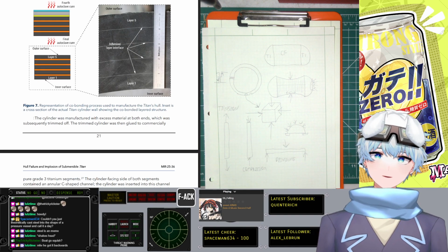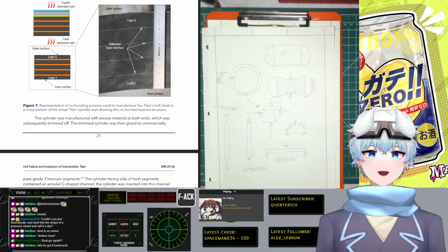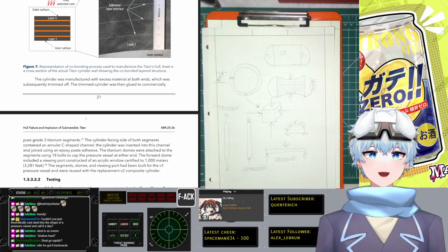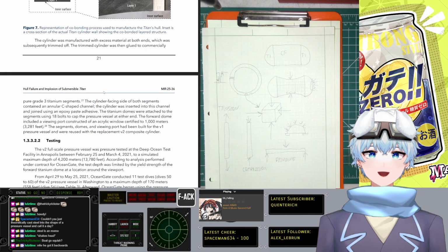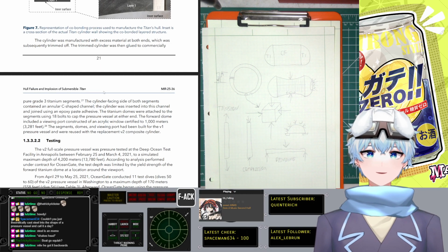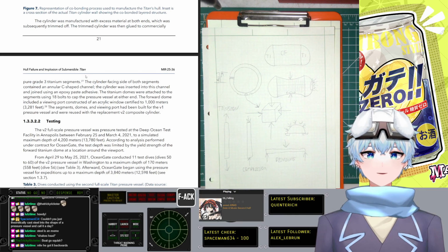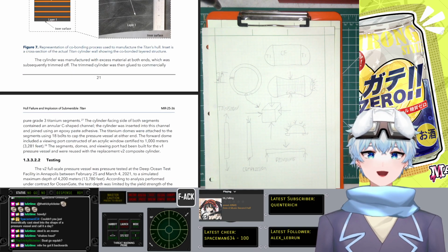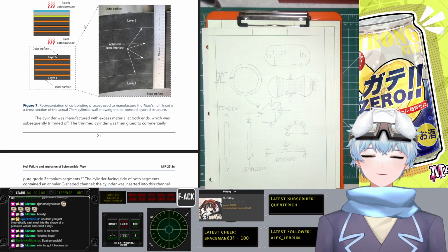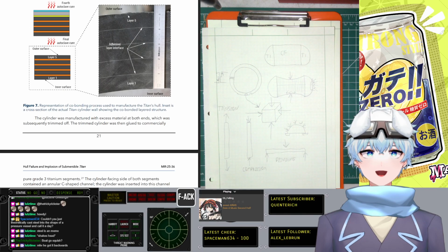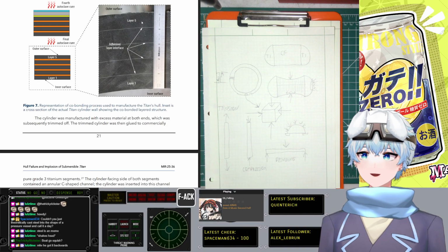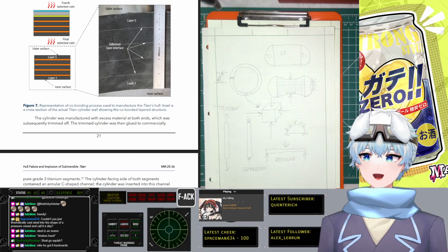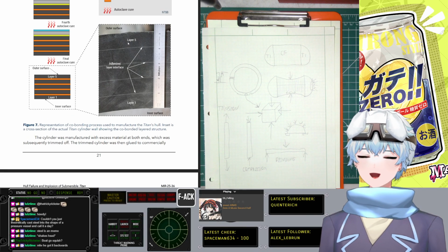So they say here, its cylinder was manufactured with excess material at both ends, which is subsequently trimmed off. It is then glued to commercially pure grade 3 titanium segments. There was a C channel to hold it in, and what ends up happening here is that because the C channel is exactly or is designed for a 5-inch thick cylinder, it doesn't fit. So they have to grind this down so it fits. That's another alarm. Big red flag. Big red alarm bell.